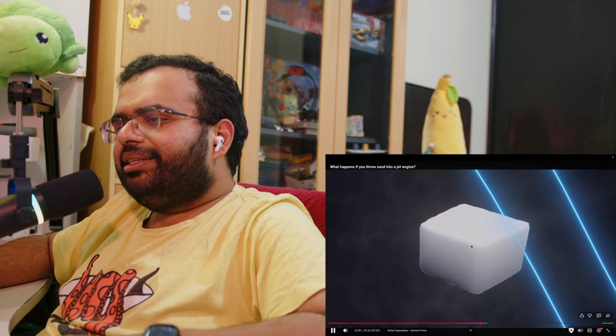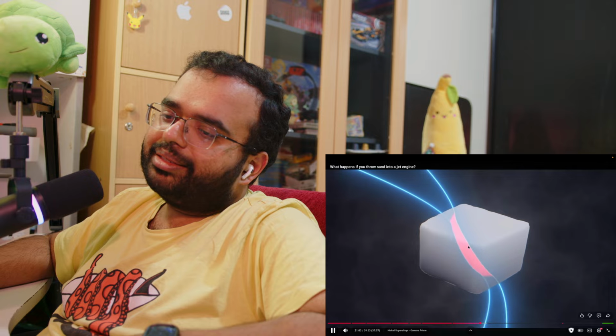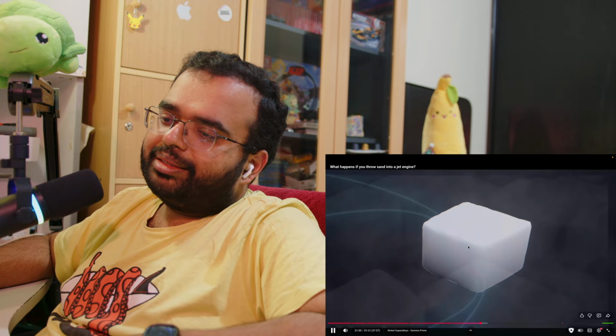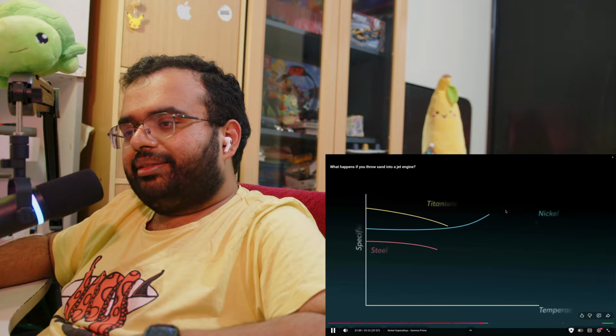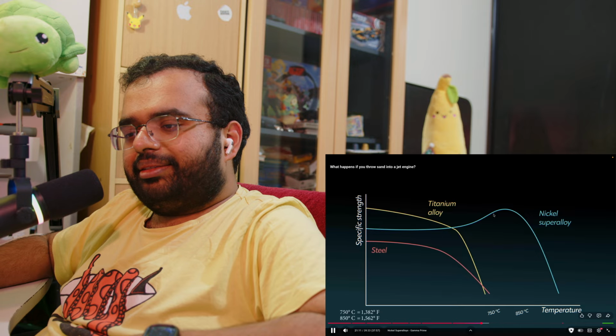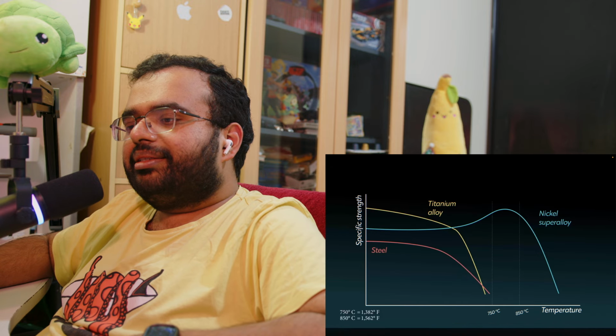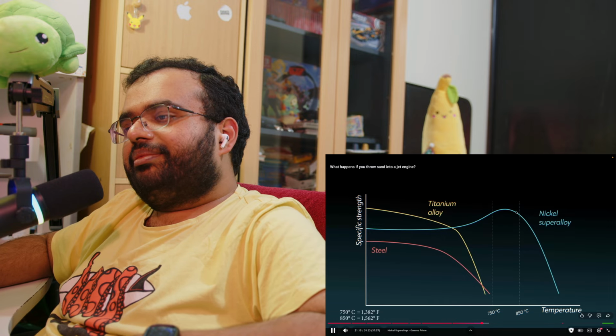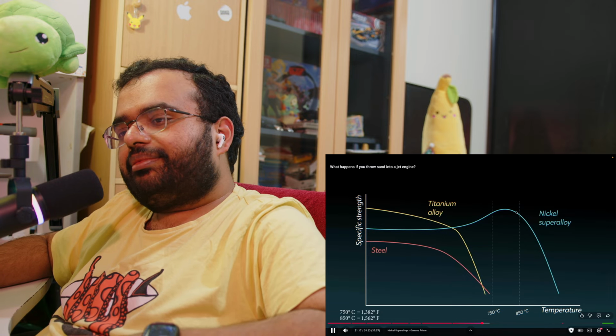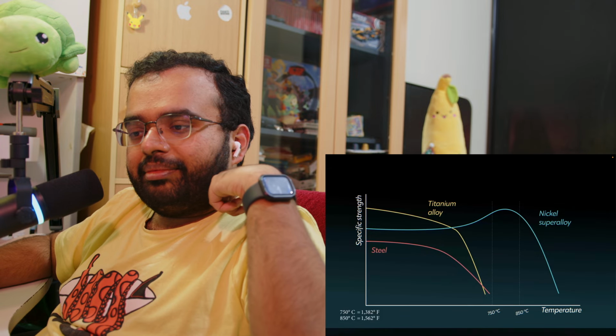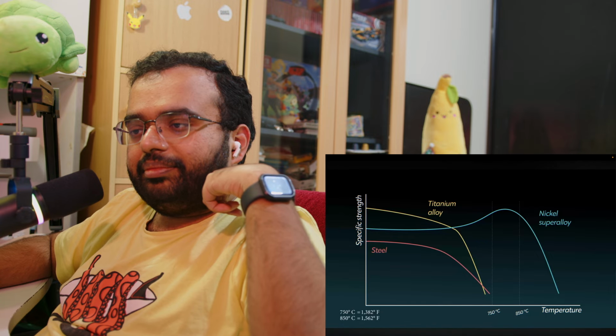So now you've got these two dislocations that are on different planes, so they can't travel together anymore. And as a result, they're both now locked into place. And you can see that effect on this graph. While steel and titanium strength drops off, in the nickel superalloy, you actually get a peak. That's because the extra thermal energy lets more dislocations cross-slip and get separated. And that shuts down the motion of dislocations.